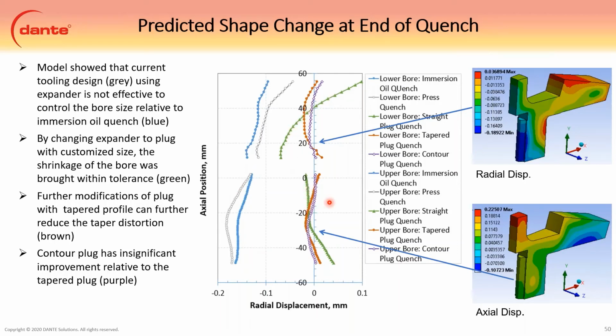So we reduced the distortion of the bore substantially. However, we end up with this big taper. So what we said was, okay, well, we can get rid of a taper by using an inverse taper. So we essentially reversed the taper in the plug. By doing that, we force it to be straight. We ended up with this brown line. We end up with a little bow now, which isn't bad. I mean, that's still pretty small.